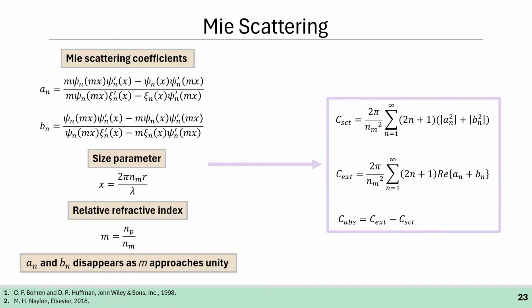And with those coefficients, we can calculate the scattering cross-section, the extinction cross-section, and the absorption one. All those parameters can be measured experimentally. Nonetheless, if we can measure only 2 of them, we can deduce the 3rd one.